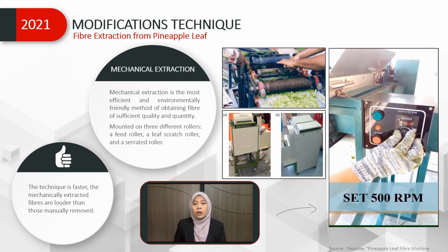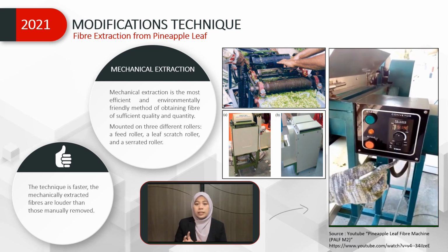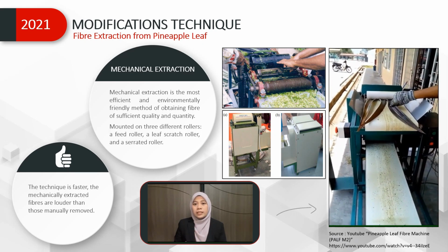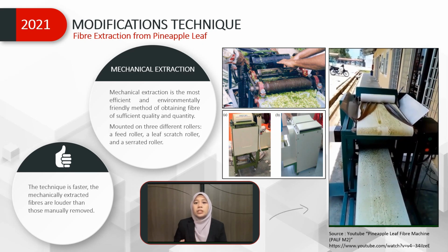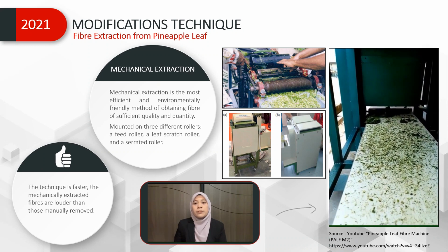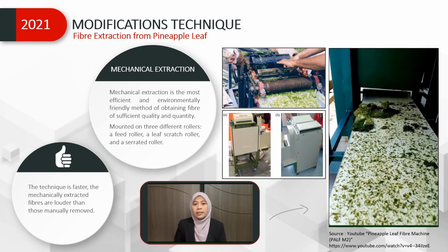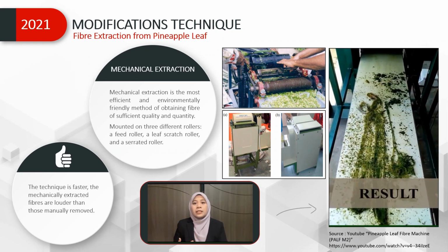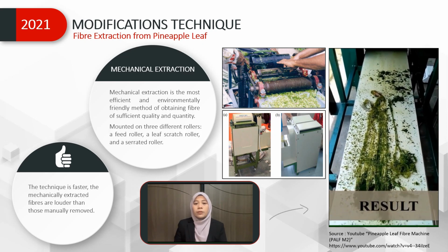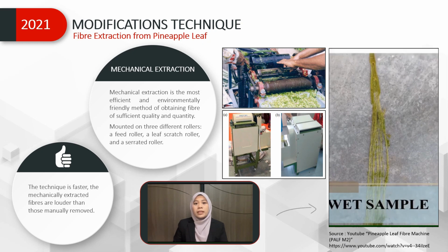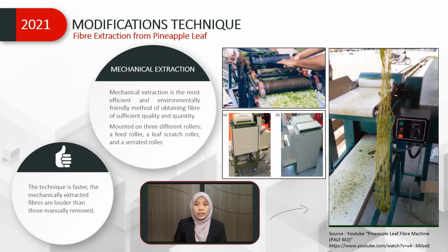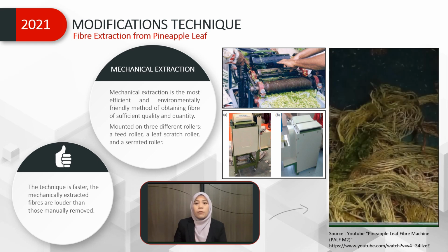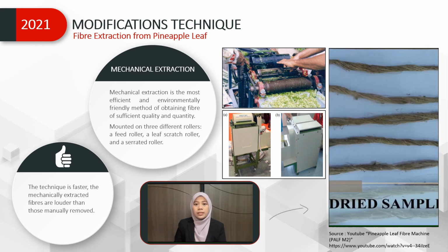Next, mechanical extraction is the most efficient and environmentally friendly method of obtaining fiber of sufficient quality and quantity. The machine usually used is called the pineapple decorticator machine, as in the figure. This machine is mounted with three different rollers: first, the feed roller, a leaf scratch roller, and the serrated roller. The method starts by passing the leaf through a feed roller, which scrapes off the waxy covering. Then the gap was created by a tightened roller. Then the leaf traveled through the thick connected blade, which smashed the leaf. Although the technique is faster, the mechanically extracted fibers are lower in quality than those manually removed.